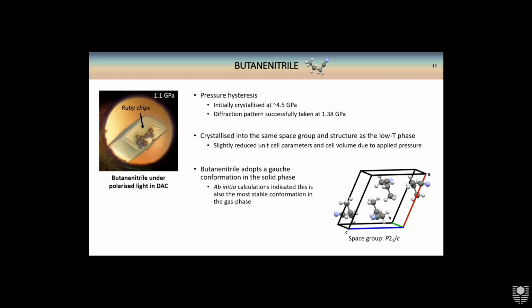And for butanenitrile, we found a similar pressure hysteresis. This time it crystallized out at around 4.5 gigapascals, and we were able to bring it down to 1.1. This time we got a much nicer single crystal, and we were able to avoid having any polycrystalline mass.